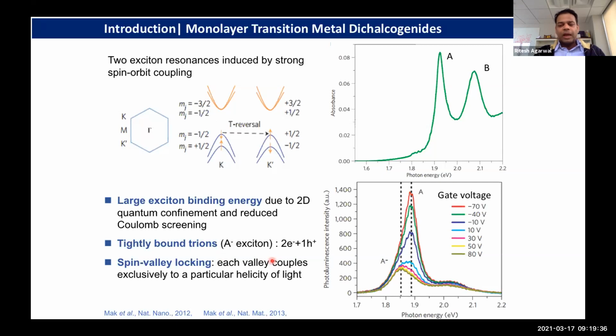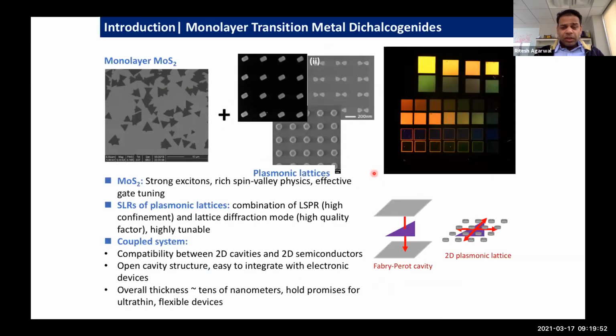The trions happen in any semiconductor material, but it's very hard to observe them because the binding energy is very weak. But again, because of inadequate screening, the binding energy of trions in these two-dimensional materials is comparable to room temperature, so one can see the signature of trions in the optical spectrum. So again, once you have a two-dimensional material, how do you define a cavity? So there are dielectric cavities, and people have done a lot of very interesting work.